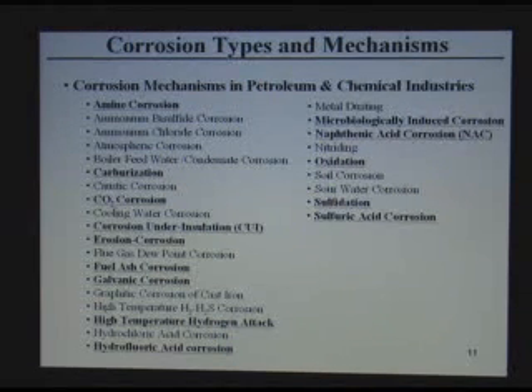Galvanic corrosion, what happens between two metals of differential potential, and then the less noble material will corrode. I will explain later. Graphitic corrosion of cast iron, where the graphite is cathodic relative to the iron, so the iron nearby corrodes, and you end up leaving only graphite, and the iron disappears. So the cast iron dissolves actually. High temperature corrosion by hydrogen sulfide. This is very common in hydrotreaters, hydrocrackers.